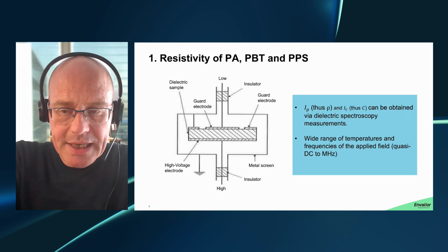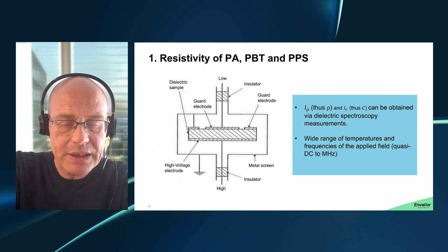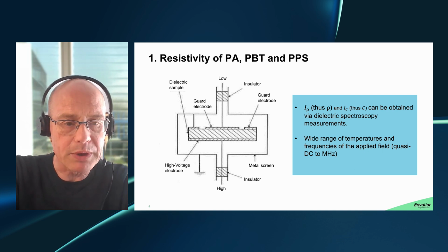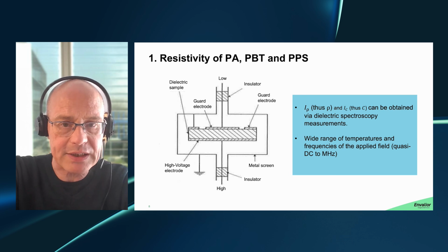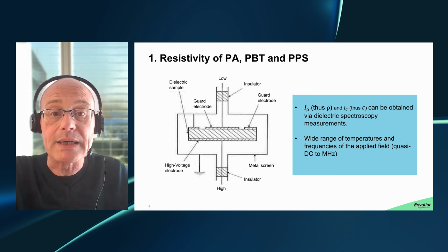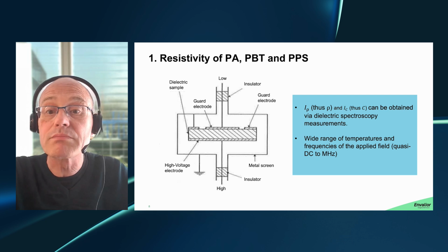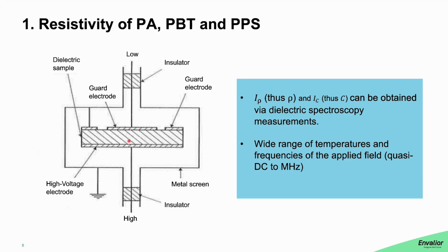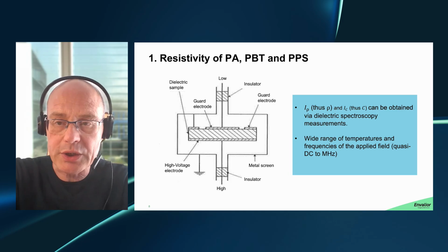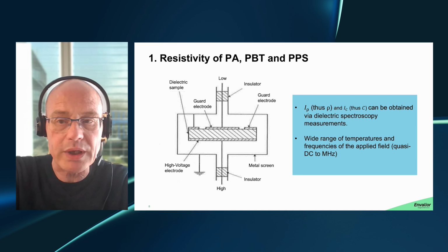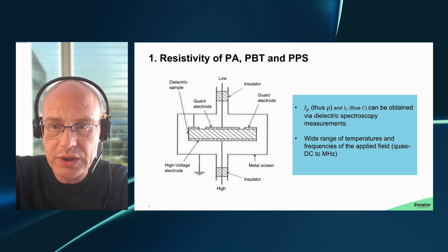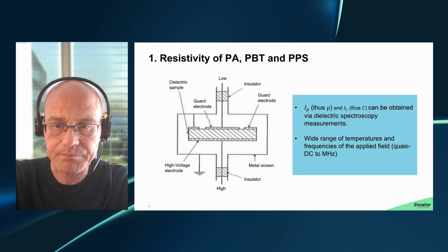This is a scheme of how we measure the resistivity of a polymer. It is done via dielectric spectroscopy. Maybe it is useful if I briefly point to here. This is the polymeric slab, and attached to that polymeric slab you have electrodes, and then what you do is you apply a voltage to that polymeric slab via the electrodes, and you pick up the current.